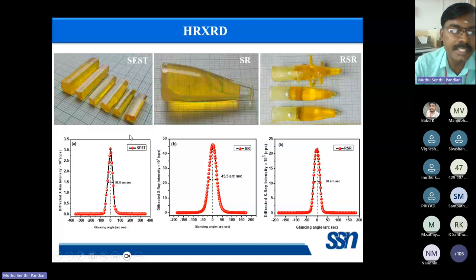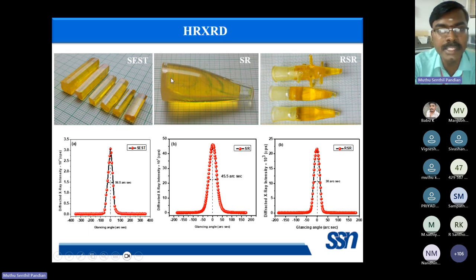To check the crystalline perfection of the SEST, SR, and RSR method grown crystals, we have used HR-XRD, high resolution X-ray diffraction. Because of the large number of microcracks, milky opaque regions, solvent inclusions, and grain boundaries, the FWHM, full width at half maximum, of this SEST method grown crystal is 56.9 arcsec. But in the case of the SR method grown crystal, we can restrict the grain boundaries, and it has a single, morphologically well-defined face. But impurity segregation is more in the conventional SR method grown crystal; we cannot avoid it in this conventional SR method. So the FWHM of this SR method grown crystal is 45.5 arcsec, but still a lot of impurities are segregated in this conventional SR method.